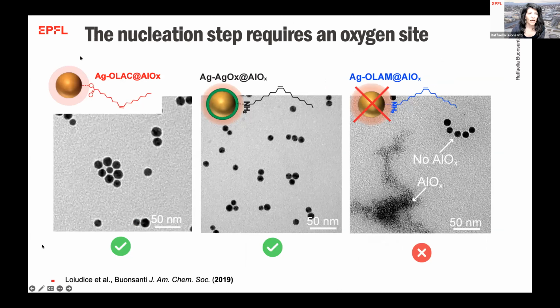And what we discovered is that we require an oxygen site. So basically here, the oxygen site can be the ligands themselves. So if we have, for example, something like oleic acid, the shell of alumina grows around the particles. Actually, you don't see the shell here because it's amorphous and because there's low contrast in the microscope. So we verify that it's there by different means.